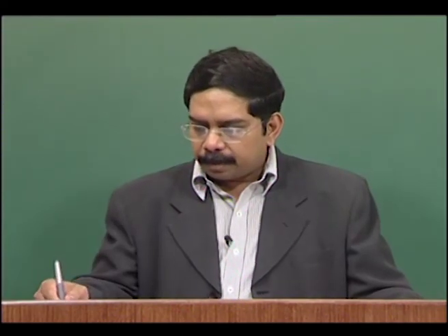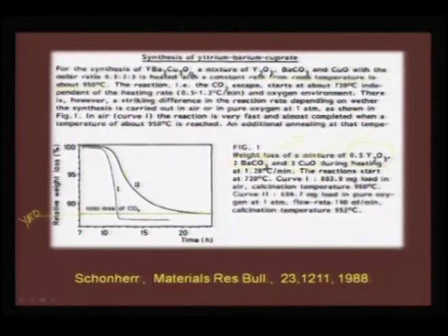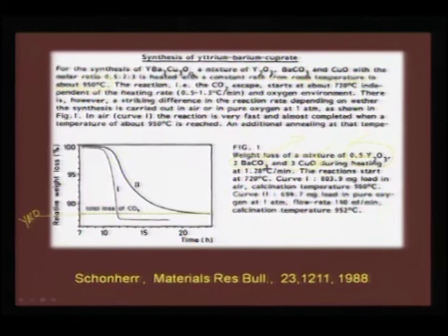above 800 degrees C. Therefore, the reaction between yttrium, copper and barium has to happen only above 800, and the nominal temperature is achieved at 950 degrees C. The problem is, when the mixture is being heated, there are chances that some intermediate compounds can form between reactive yttria and copper oxide, and when that happens, the stoichiometry suffers. So, this is the problem with such a superconductor.